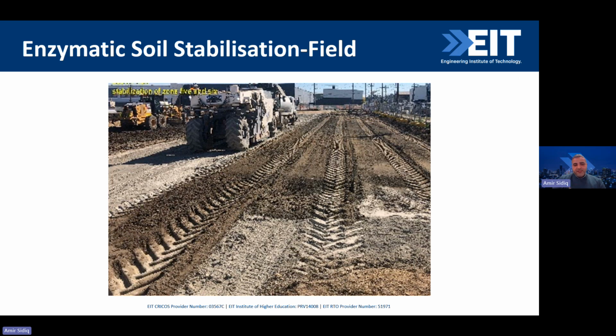How they actually use the enzyme throughout the site: we use this particular construction equipment. There's a tank, and it's connected to this enzyme spreading machine. So you adjust the water coming into this machine with the particular enzyme content, and it sprays it equally, distributing it through the entire site. Every location, every spot gets the same content as required. With other methods, where they just spray by using a tank, for example, just mixing the enzyme with water and spraying, that does not distribute the additive equally throughout the entire site. So there are different instruments and equipment used on site for perfect distribution of additives, particularly when we're talking about liquid additives.